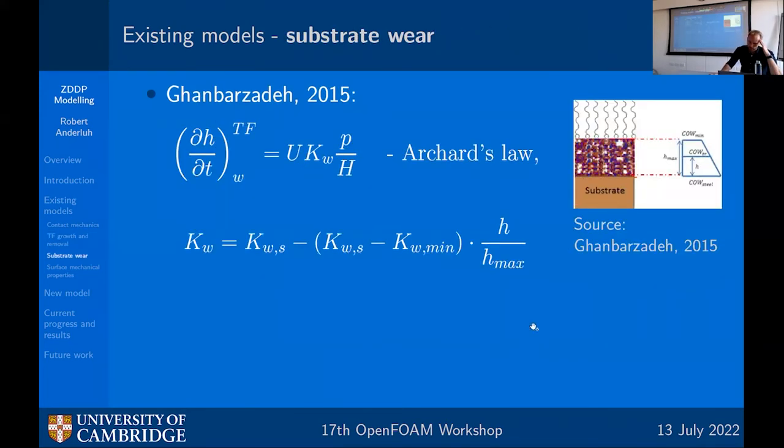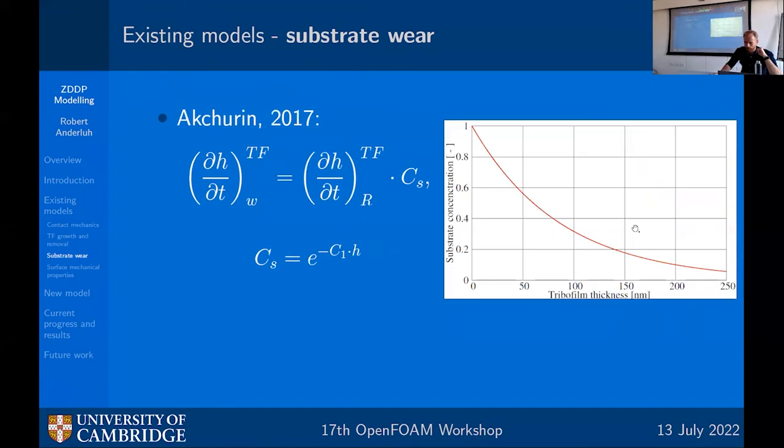Okay, after we have the tribofilm growth and removal, how do we approach modeling substrate wear when we have that information? In 2015, Ghanbarzadeh was using Archard's law, and the way he was using the information about the tribofilm was that he had a linearly dependent dimensionless wear coefficient that he was getting from the local thickness of the tribofilm, as shown in this image.